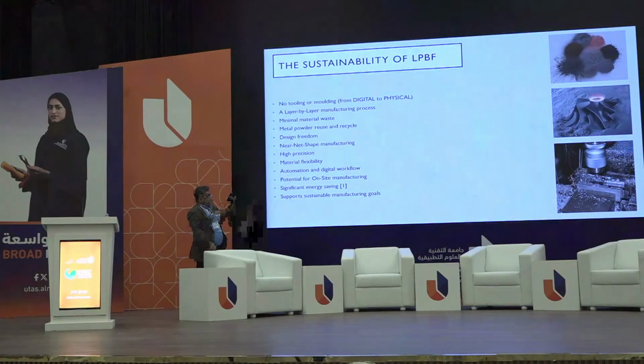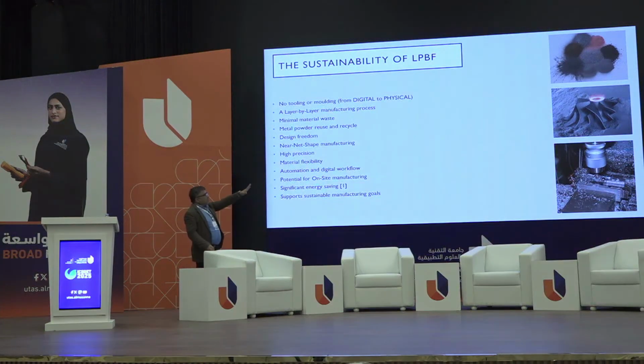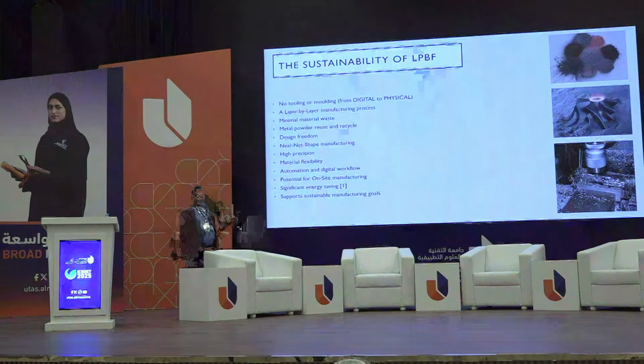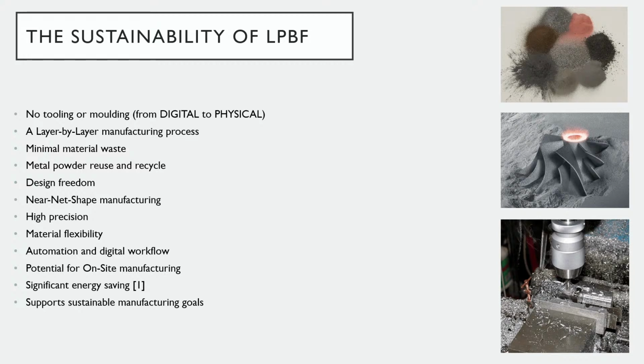All the powder around it will be reused, like you saw in the video when I was removing the powder with the brush. So all the powder around it will be reused multiple times before it's recycled. So still you recycle it. During the reuse, you may sieve just to get rid of some affected particles, and you can mix with fresh powder if you like. Usually biomedical companies use 100% fresh powder, so they don't recycle. The last figure is the traditional method, milling, and you can see the swarf and the chips. These all have to go to recycle.